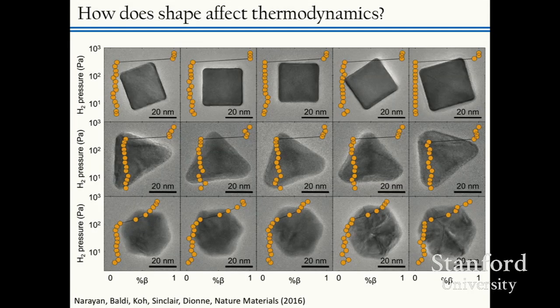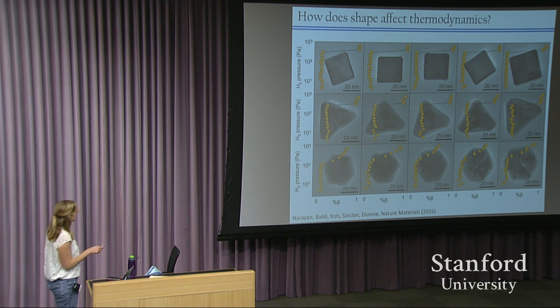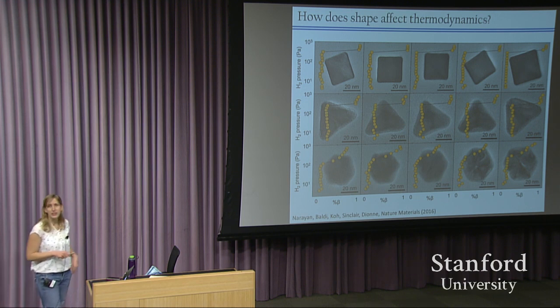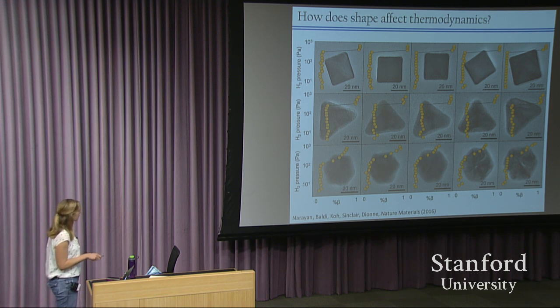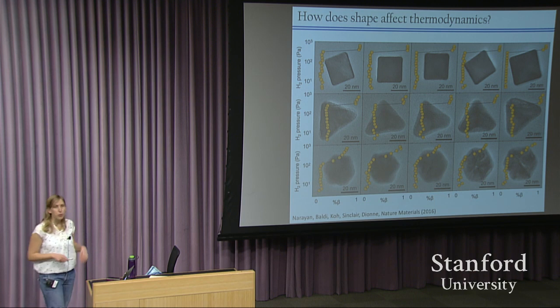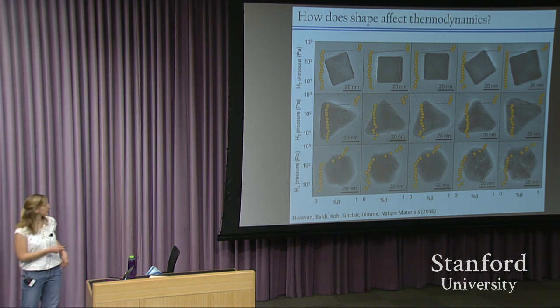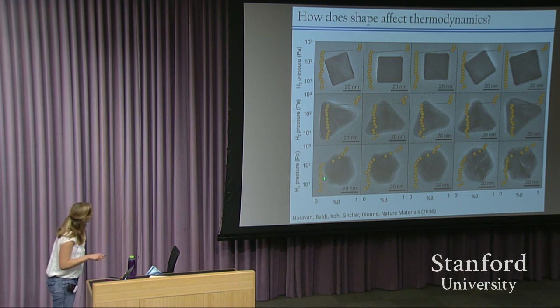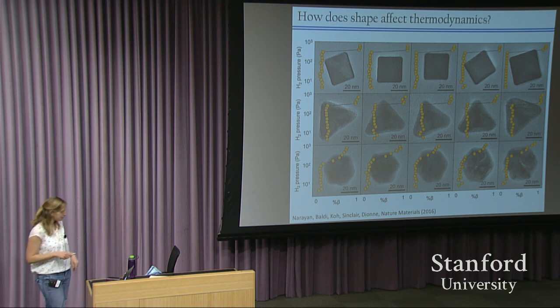If we look at cubes, pretty much regardless of size, as long as they're above about 15 nanometers, we wind up with these very sharp transitions. Here, I'm now plotting the concentration of beta on the horizontal axis. So cubes load abruptly and have sharp transitions. It also turns out prisms, regardless of size, have these very sharp transitions with no points in the coexistence region. But if we look at icosahedra, their isotherms are quite a bit more sloped, almost more like those ensemble measurements. And you'll also notice that once we're in the beta phase, we don't have as high a hydrogen concentration as we would have in these single crystalline nanoparticles.